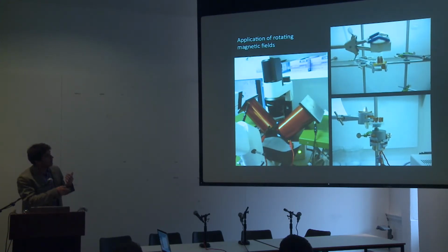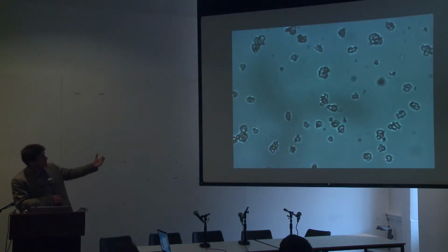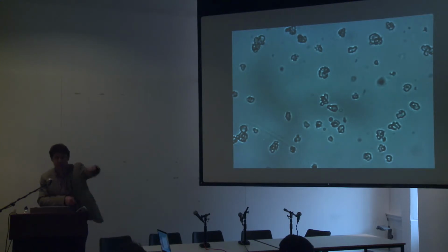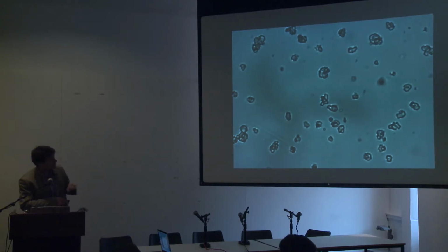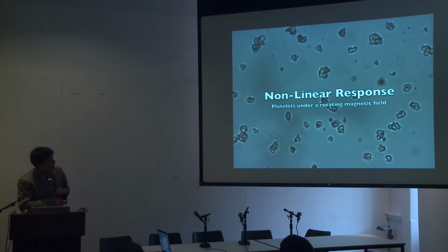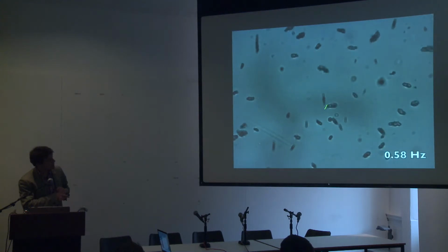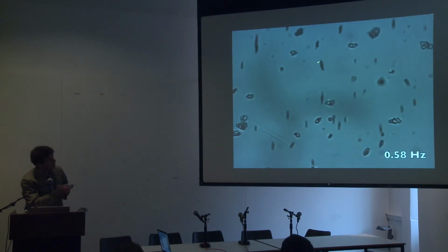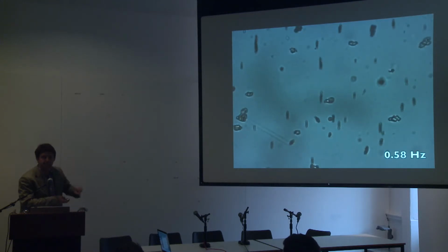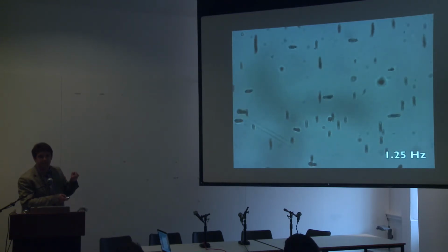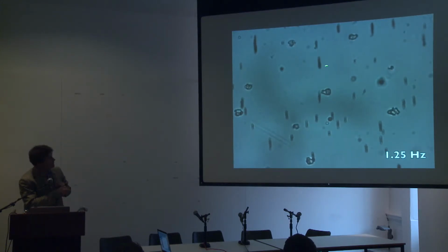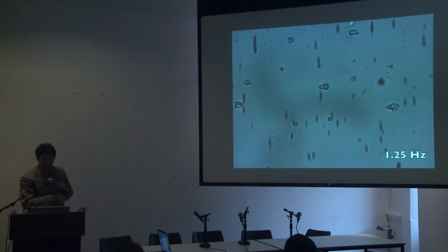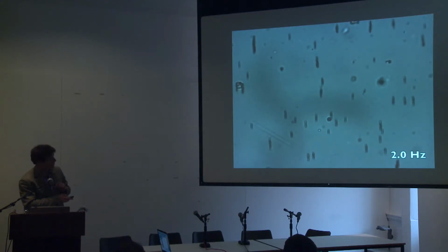So we can do this on slightly larger samples to measure the mechanical properties. We can do this under a microscope to study this alignment effect. Here's an example, again, of the little microplatelets, and now I'll apply a magnetic field in this direction, and you'll see that some of them align right away, but some start rolling, and then I'll start increasing the speed of this rotating magnetic field, and you'll see that at a critical frequency, a critical speed, all of them will align in this biaxial fashion, which allows us to really control in 2 dimensions the orientation of these platelets.